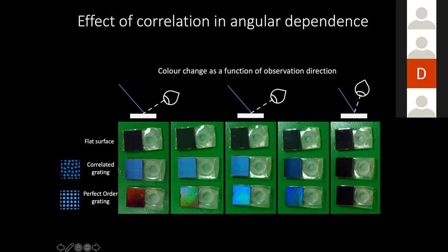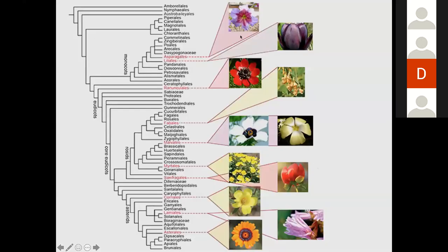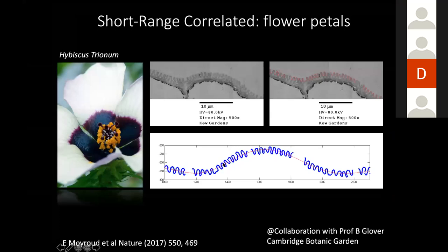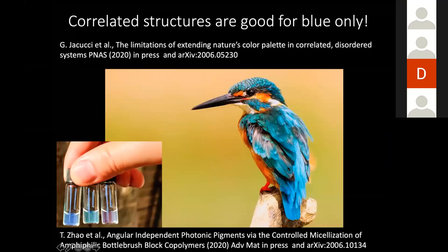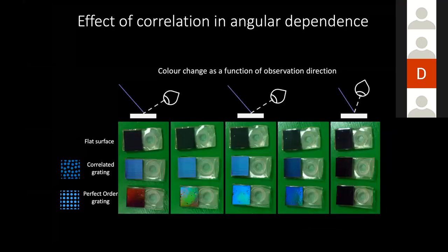and you actually obtain, in fact, a correlated structure. You see now how the color looks as a function of different angle is not anymore, like as I was telling you before, changing the color as a function of the angle, so iridescent, but it's much more angular independent. And this is pretty cool for us to discover, because when we went to do a little bit more digging and we started to analyze different flowers coming from different families in the entire phylogenetic tree with collaborators in plant science, Beverly Glover and Edwige Moyroud, what we realized is that flowers have actually converged to have an optimal amount of disorder to obtain this angular independent cue. And the reason why they do that is because they are more visible. They have done some tests with bees, really a behavioral experiment.